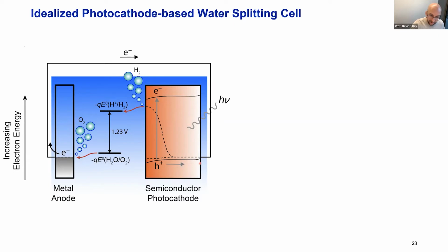And the holes are now in equilibrium with the Fermi level over here, the electrochemical potential of the anode. We see that this is now more positive, or let's say lower in energy, than the electrons in water. So now it's downhill in energy for the electrons to move into the anode, and so we're going to oxidize water to oxygen. This difference, the thermodynamic difference between these two reactions, is effectively the energy that can be stored by doing this reaction.